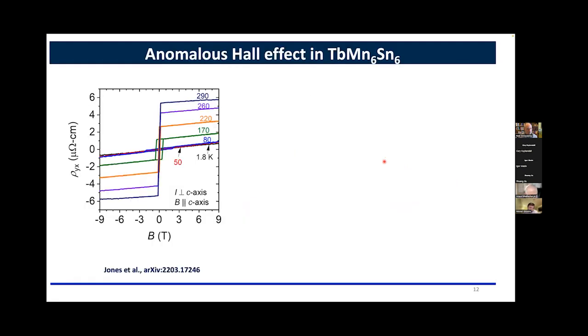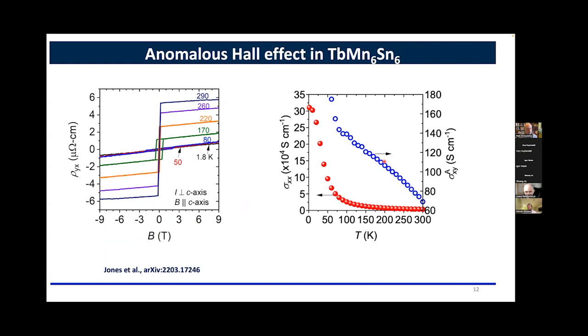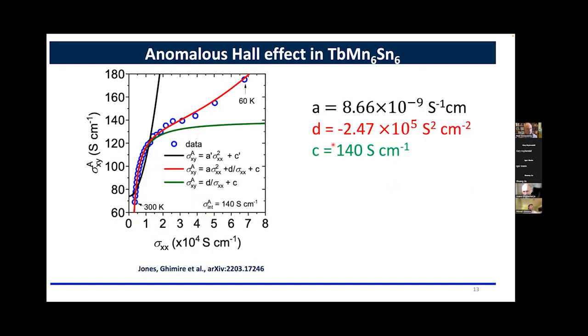Another part that we saw in the talk earlier is about the anomalous Hall. Remember, this is a ferrimagnet. If you just measure an iron ferromagnet, then you see anomalous Hall because there is a spin splitting. A ferrimagnet is no different than a ferromagnet, so there is spin splitting in this material. And one of the ways to understand this intrinsic contribution from the band structure is by doing the scaling behavior. And for that, we need to measure the rho xx and rho xy, which was already discussed earlier in this talk. So we measured the sigma xx, and then sigma xy, the anomalous part, and we tried to do the scaling behavior here.